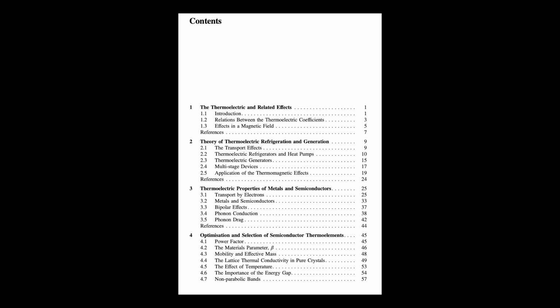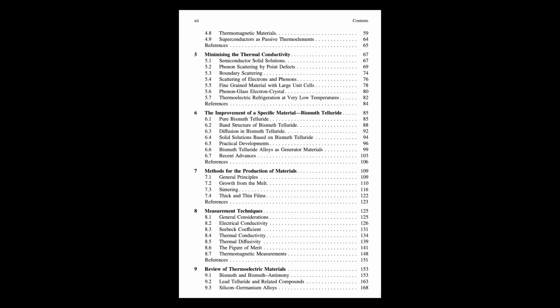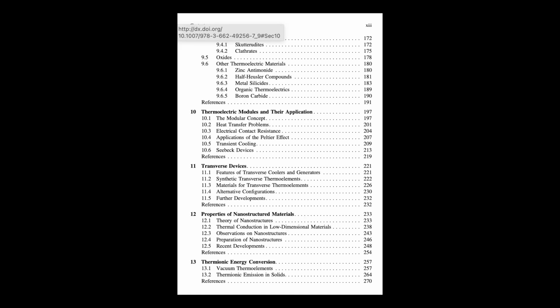Interestingly, the book notes the ideal Fermi energy for this maximum is often quite close to zero energy, near the band edge. That feels a bit odd. Wouldn't you want lots of carriers, a high Fermi energy? You'd think so, wouldn't you? But it's not just the number. It's also their energy distribution relative to the Fermi level. A higher Fermi energy means more electrons, sure, but their average energy difference might not be ideal for generating the biggest Seebeck voltage. So sometimes slightly fewer carriers, but with a better energy setup, gives you the best overall power factor.